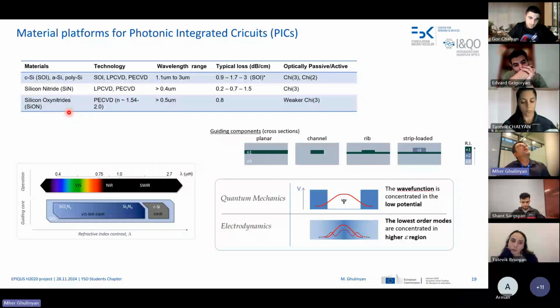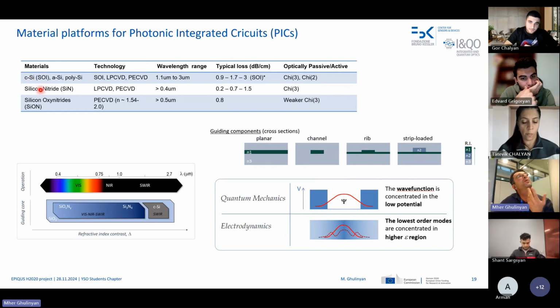The technology we use here is mainly silicon technology, but saying silicon does not mean that we work only with silicon. The materials we use are crystalline silicon and the family of silicon-related materials like silicon nitride and silicon oxynitride. These are different technologies, but they are all very friendly to the CMOS, complementary metal oxide semiconductor, technology of silicon. You cannot, for example, process here materials that are enemies of silicon, like gold or other metals that easily go into silicon and create impurities. They are not good, especially when creating electrical devices.